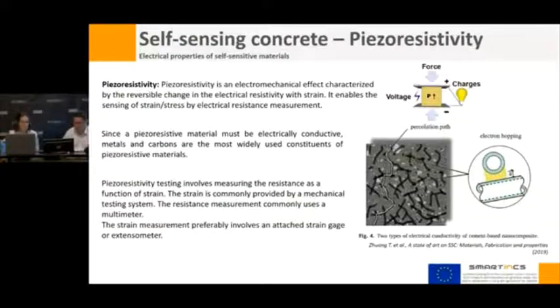For the second parameter I want to talk about, piezoresistivity is an electromechanical effect that is characterized by a reversible change in the electrical resistivity with strain. It enables the sensing of stress and strain by electrical resistance measures, as Jean-Marc told you before also. To define a material as piezoresistive, it must be electrically conductive. So we need to make concrete more conductive by means of the addition of metals and carbon materials, which are the most common ones.